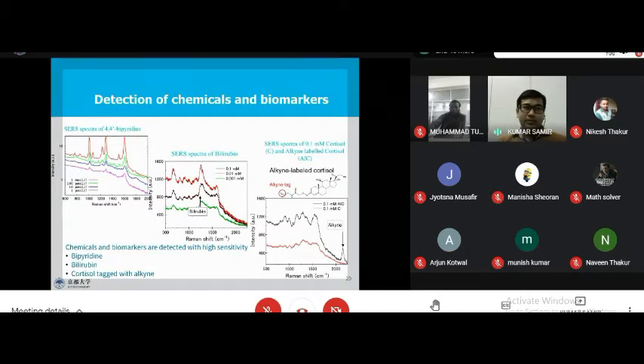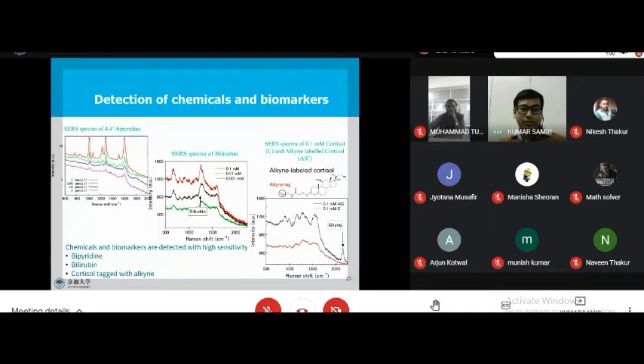So this gel removes the limitation of the rigid substrate, which you cannot directly apply to any surface and collect the sample from the surface. But using this gel, you can apply it on a surface, and you can heat it after drying, or you can take the measurement even before drying, also from the bag, because it's transparent.